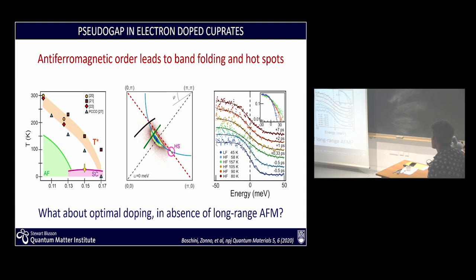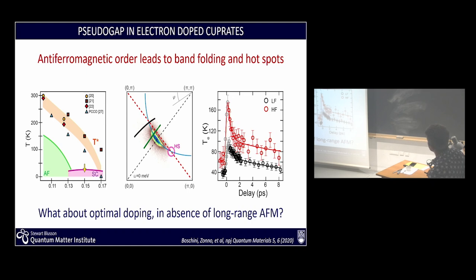We can extract a Fermi-Dirac distribution for different delays and different pump fluences. So each of these curves corresponds to a different electronic temperature. You can see that going up, the Fermi edge gets broadened out. It's a higher electronic temperature. So effectively, we can plot, as a function of delay, the electronic temperature for different fluences of the system. So you excite the system.